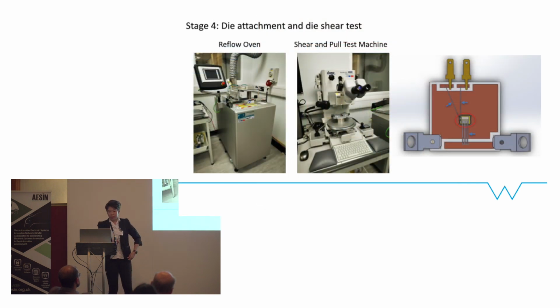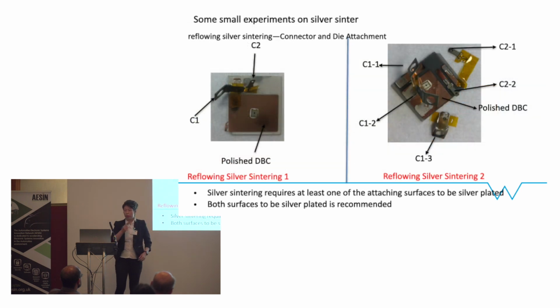The next step is die attach and die shear test. On the left-hand side is a reflow oven used for the die attachment. And on the right-hand side is a Dage tester, which is used to do the shear and wire pull tests. During our experiment, we tried different reflow sintering procedures, silver sintering procedures, for both die attachment and connector attachment.